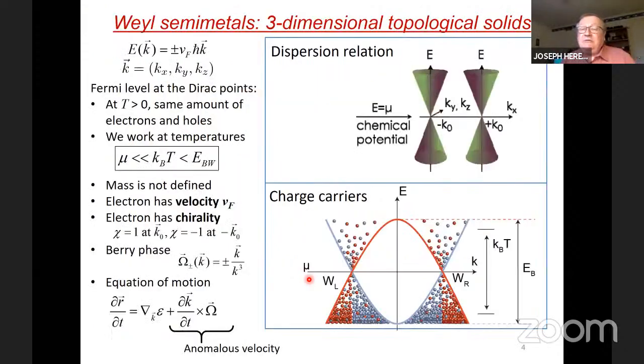So, a very quick introduction to semimetals, the three-dimensional topological solids. The dispersions of the electrons in them are linear dispersions, so there's only a Fermi velocity and a K vector. The Weyl cones, which are characterized by these dispersions in 3D, come in pairs with opposite chirality. We will be working with the chemical potential very, very close to the Weyl point. The chemical potential will be much smaller than the temperature and smaller than the bandwidth of the Weyl. So the Weyl bands have a certain amount of overlap here.